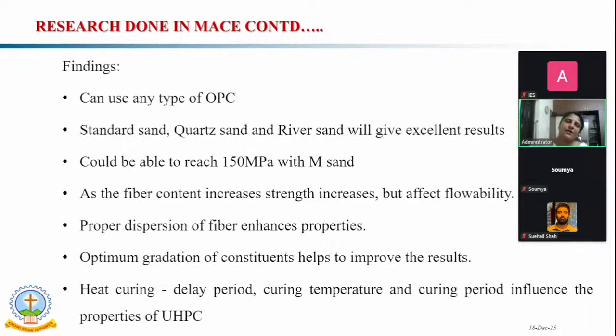After all the parametric studies, our findings are: we have considered many ordinary Portland cements, that means different brands of ordinary Portland cement. Then we found that we can use any brand of ordinary Portland cement. That all works very well. In the case of sand, we have considered standard sand, quartz sand, river sand, and manufactured sand. The best results we got are from the standard sand, quartz sand, and river sand. We could reach only up to 150 MPa with the M sand. But due to the availability of standard sand and river sand, finally we moved on with the quartz sand.